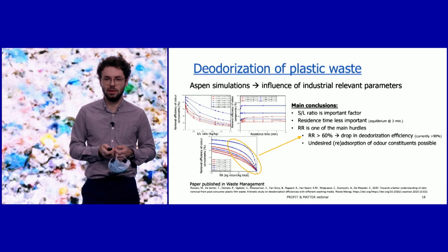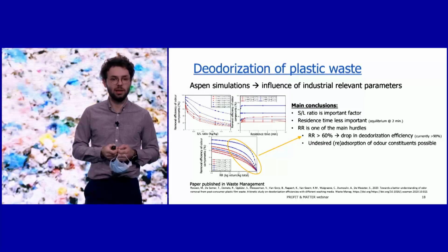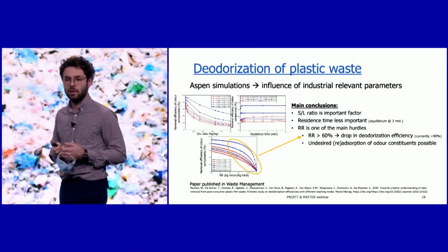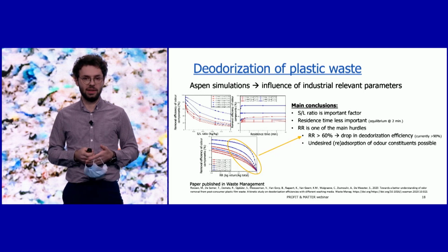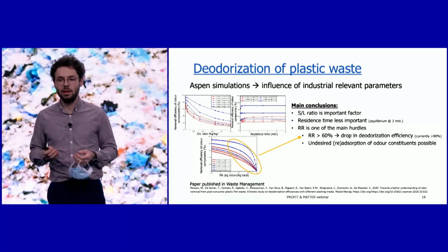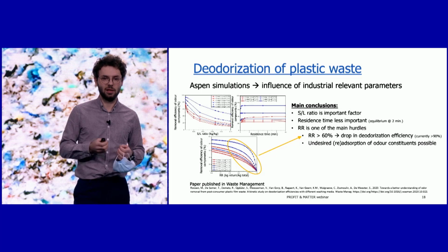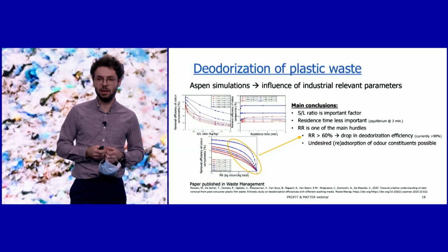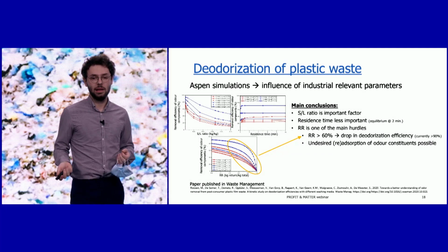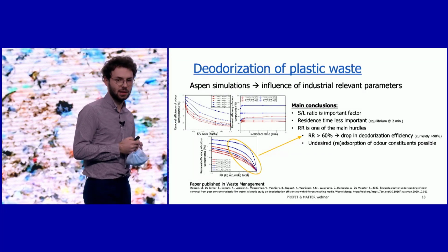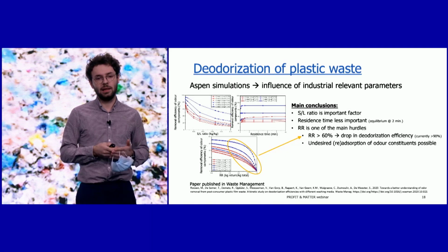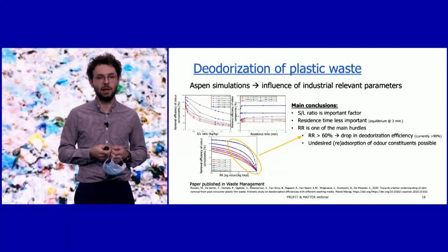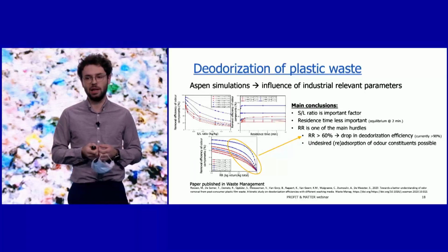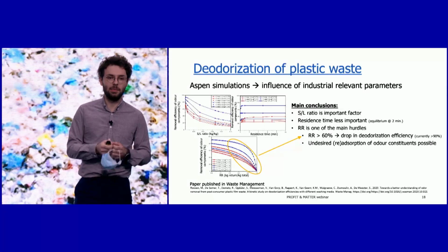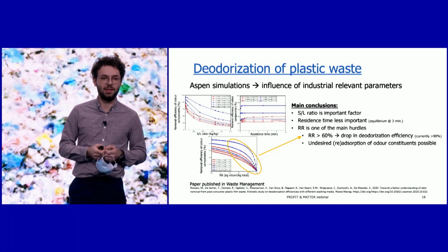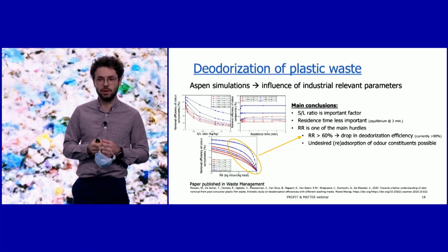But our third factor, the recirculation rate, again is a quite important factor and maybe even one of the main hurdles to increase the deodorization efficiency, because what we saw is that applying a recirculation rate of more than 60%, as you can see in the yellow circle, significantly drops the deodorization efficiency. Knowing this, and taking into account that currently most companies apply a circulation rate of more than 90%, this explains the relatively low deodorization efficiencies that are currently achieved.